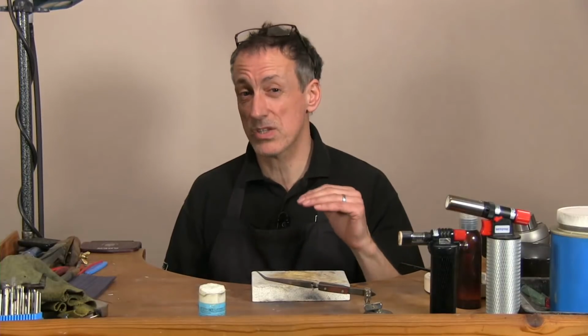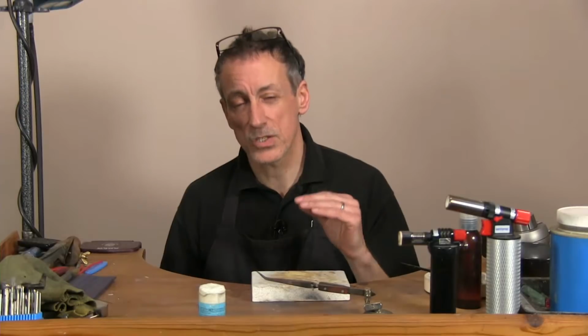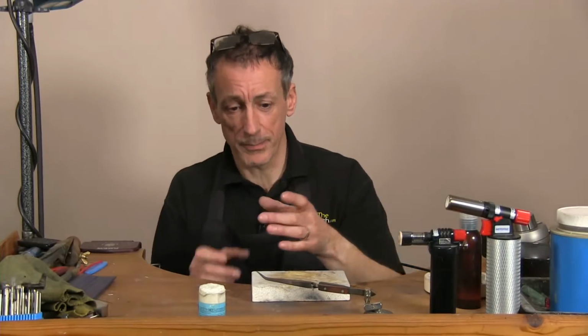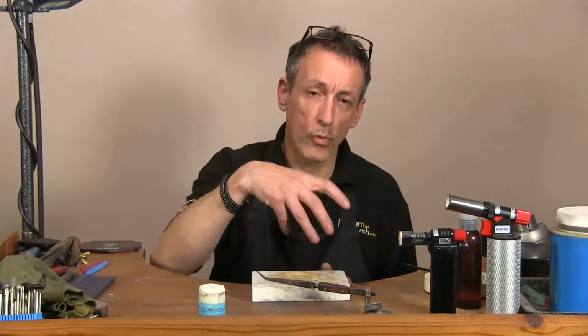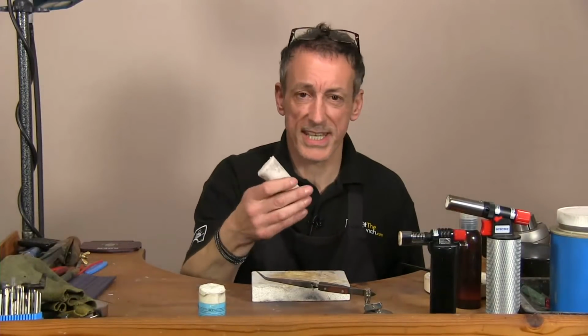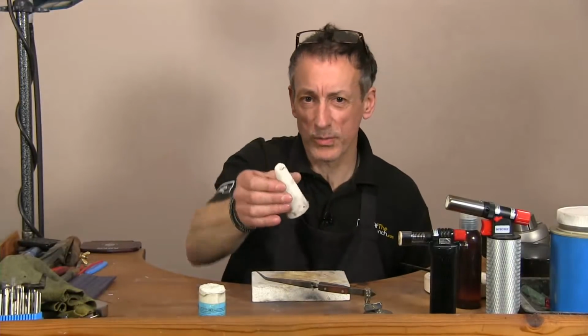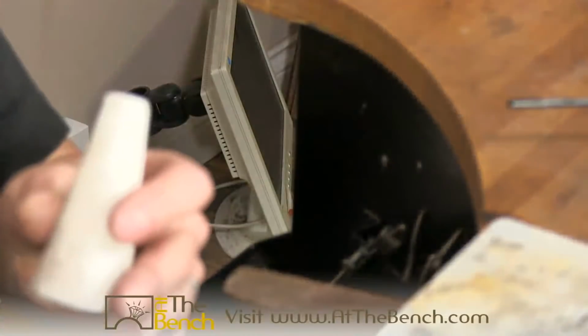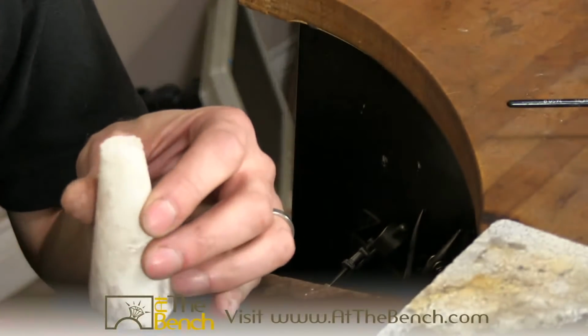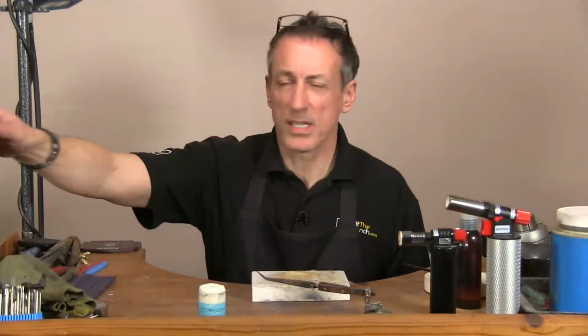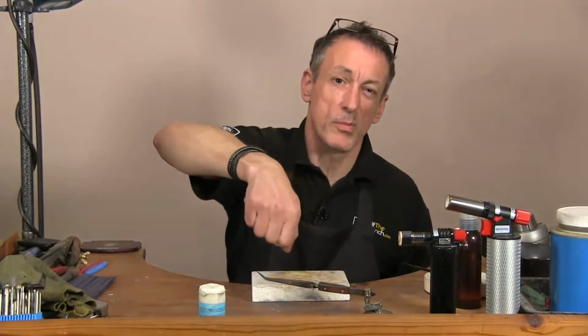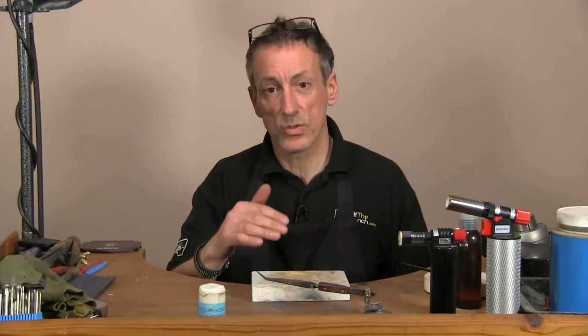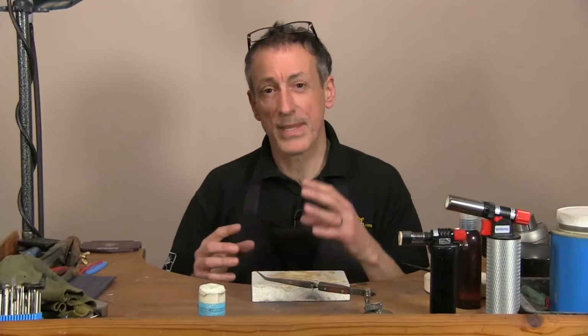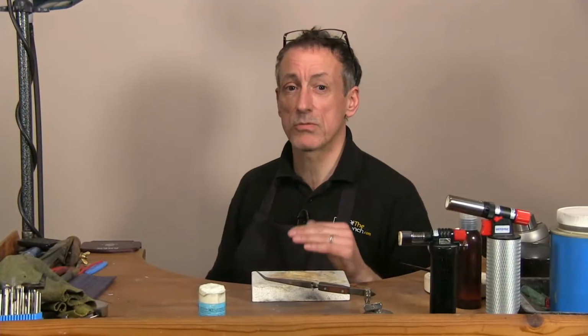Will you get fire scale and fire stain when you roll it? I think if you do have that sort of flame, yes, you would. But also when you come to melt your silver down in your crucible, don't forget to put some borax. Get some powdered borax, or just get your cone and squidge the end of the cone. That's why this cone is a bit melted and flat on the end, because we just use that to squidge down on top of the molten silver. And if there's a layer of borax or flux over that molten silver, it will protect the silver from absorbing too much oxygen. So just take care when you do it, but don't melt the silver down too many times.